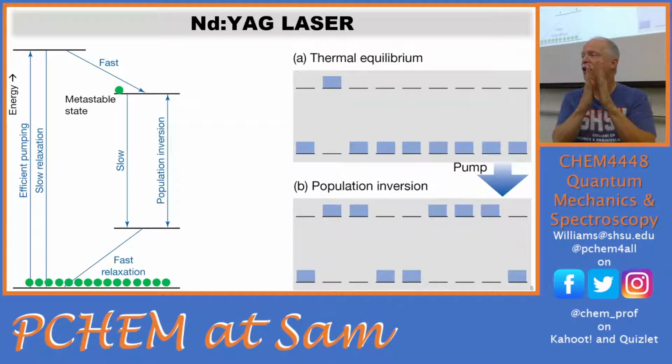So if you want a really narrow, high-resolution laser, you want a perfect crystal, and they'll grow these crystals really slowly out of a molten yttrium aluminum garnet, and they'll just pull on this crystal very slowly so that they make a perfect crystal structure at the right proportion of yttrium and neodymium and so on.